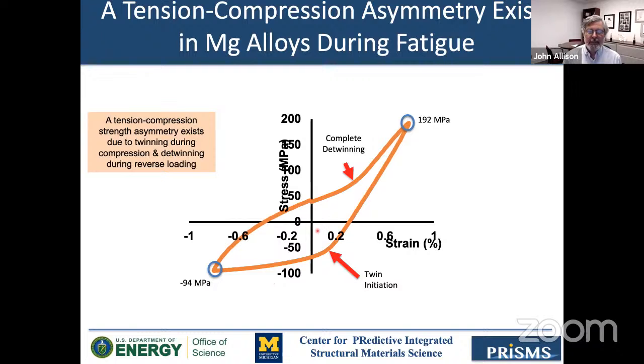And so this is what happens because of this slip anisotropy. This is a typical hysteresis loop. In this case, this is a magnesium aluminum alloy. If we start loading in compression, we get twin initiation. Then we're out here and we reverse the load. At a certain point, we get complete detwinning. Then we get normal deformation modes through basal or prism slip. And then we reverse that. And so you can see a couple of things. You get this funny shaped loop.